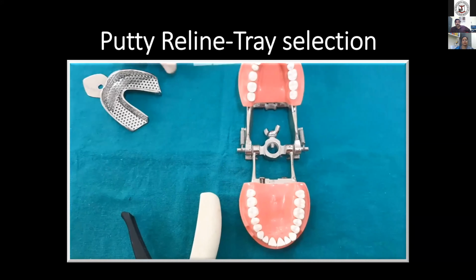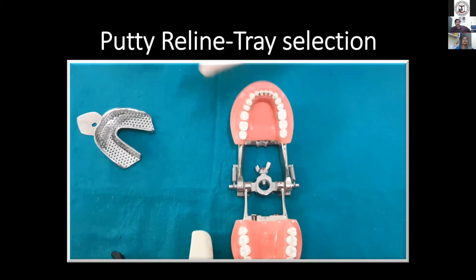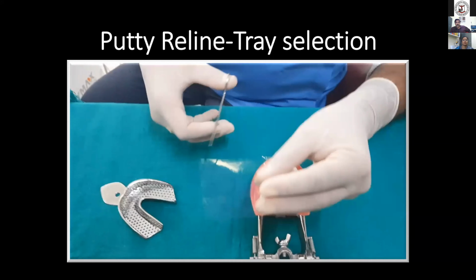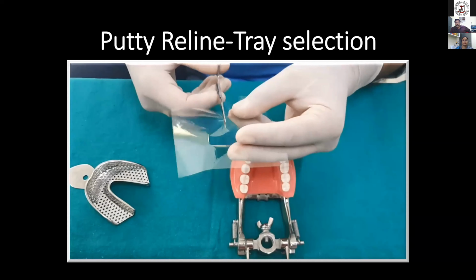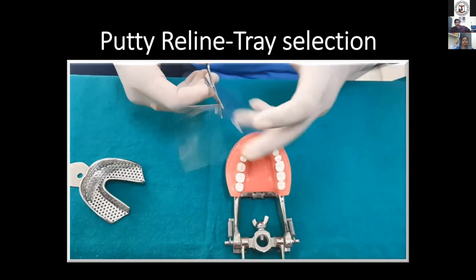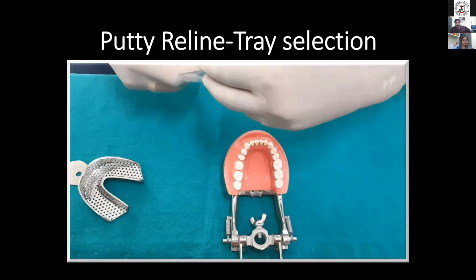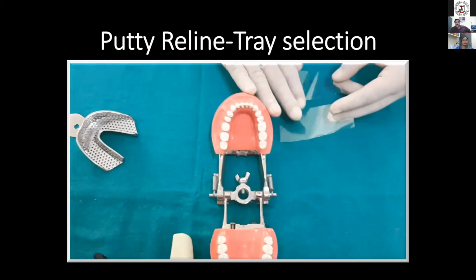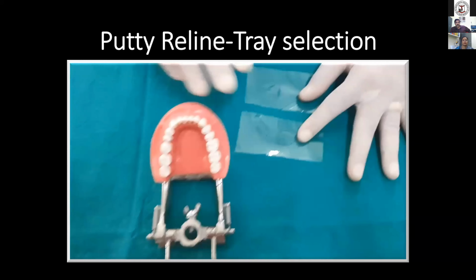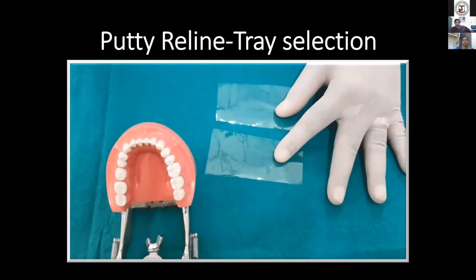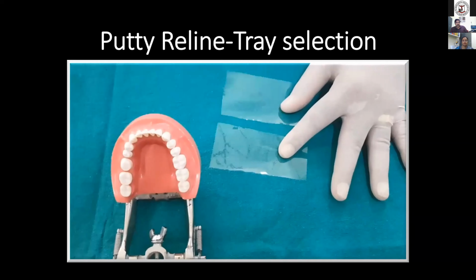A spacer has to be provided for the light body material. Otherwise, hydrostatic pressure inside will compress the elastomeric material, resulting in rebound and an undersized die. Two sheet thickness of cellophane sheet is used as a spacer. The spacer has to be cut in two pieces.